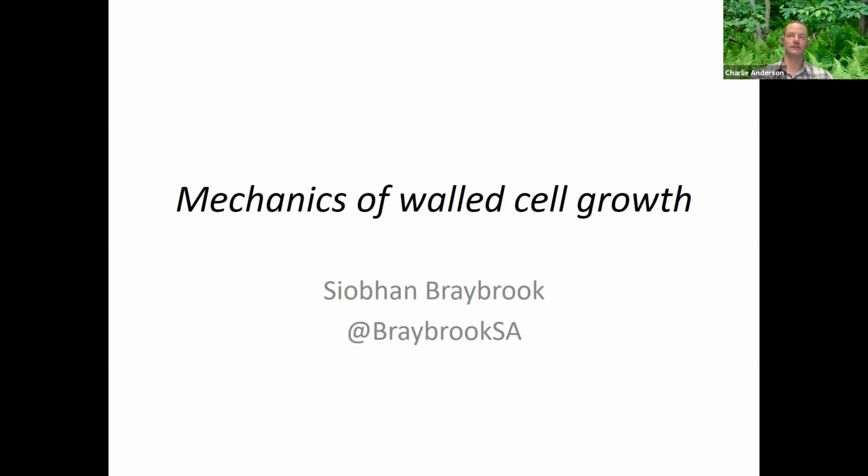The thinking there is that because there's a lack of xyloglucan interacting at the interface between cellulose microfibrils, that changes those interactions in such a way that prevents the cell wall from being acted upon by those expansin proteins that I mentioned, but can actually make the cell wall a little bit more compliant, right? So it's more stretchable but less expandable, which sounds weird. There are some of these non-intuitive mechanical properties of plant cell walls that we wrestle with as plant biologists. But the thinking is that the interaction is aiding in the expansibility as mediated by the proteins that the plant produces to control its own growth, rather than it being a purely mechanical pressure-driven process.